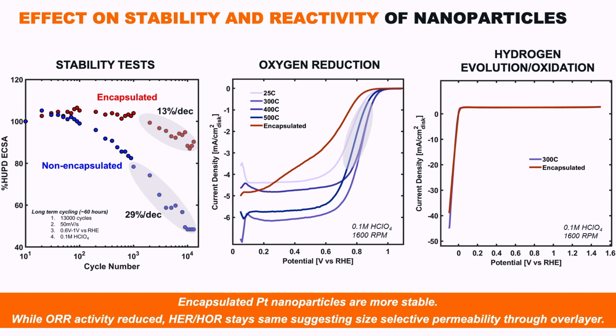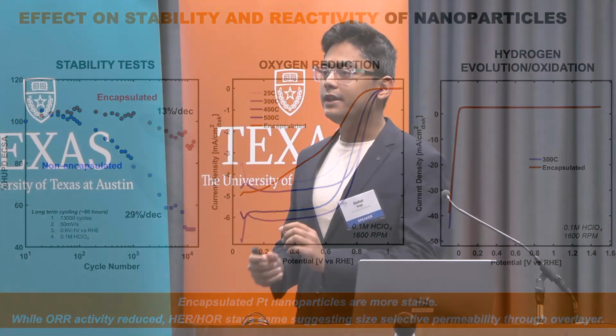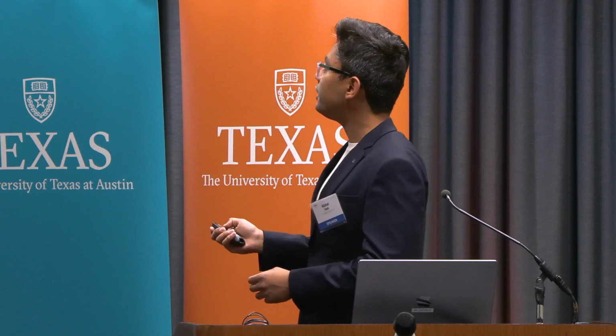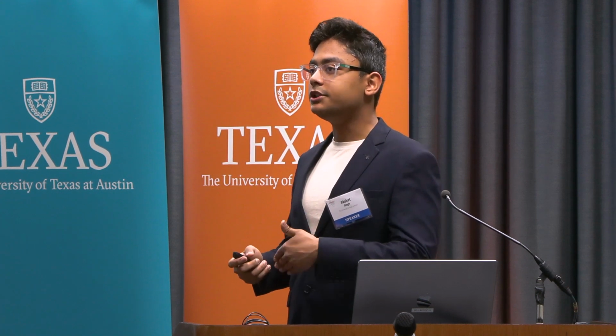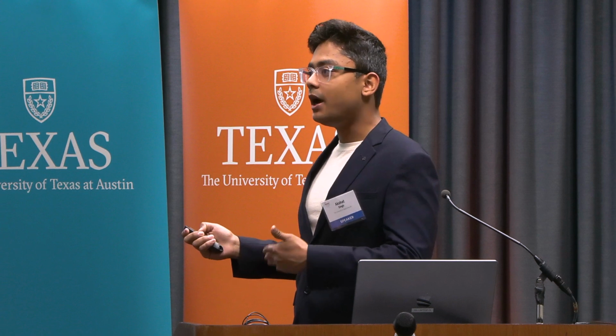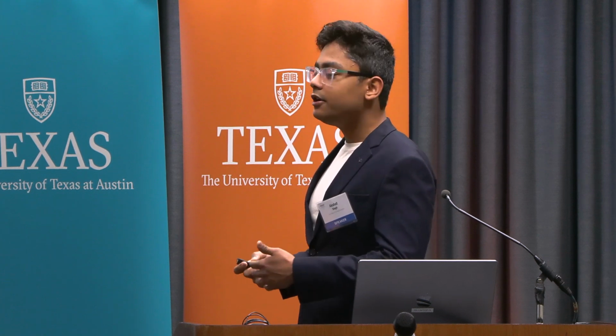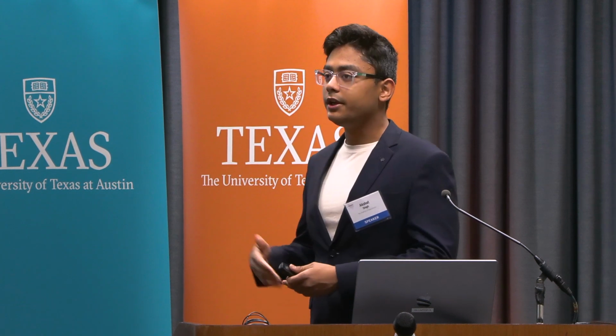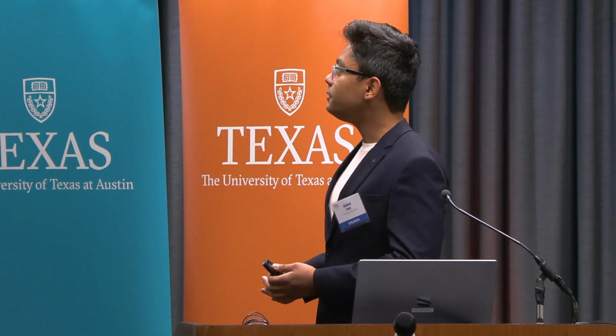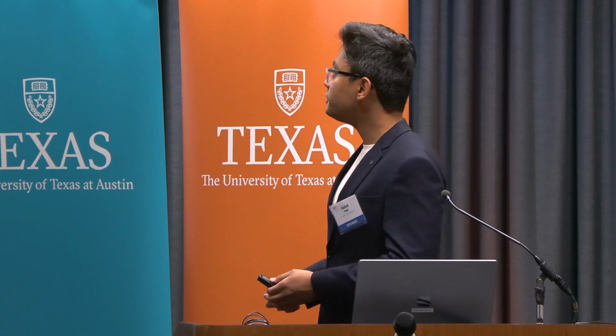And then we also saw that there was a reduction in the oxygen reduction activity for the encapsulated catalyst. However, the hydrogen evolution oxidation reactions activity stayed unchanged, suggesting that the overlayer can probably act as a size-selective membrane of sorts, where it's allowing the permeation of smaller molecules or atoms like proton. However, it's hindering the accessibility of larger molecules to the platinum that's under the overlayer. So, yeah, thank you. That's all.